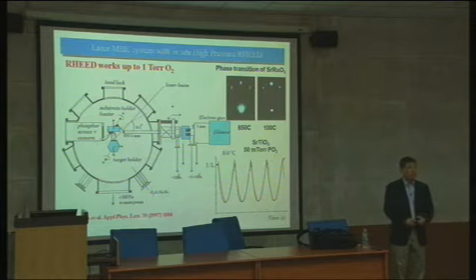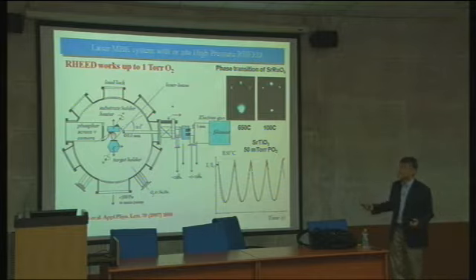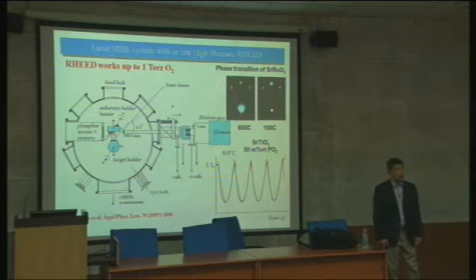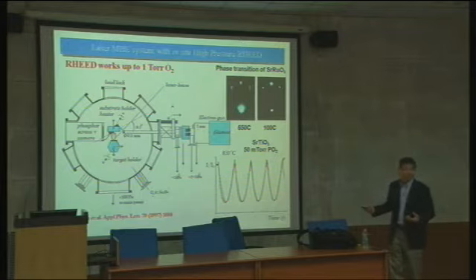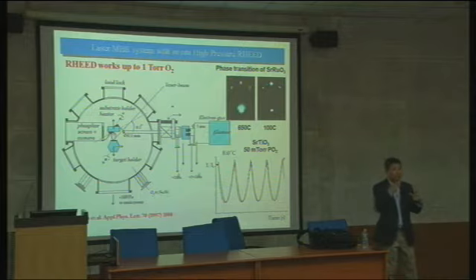Then what happens? You burn the filament. So you don't want to have any oxygen on the filament side, but on the vacuum chamber side, I need a lot of oxygen. Then how do you actually do those two things? And another problem here: you have a lot of oxygen here, and oxygen gas molecules scatter the electron beams. So that means the mean free path of the electron beam can be very short.